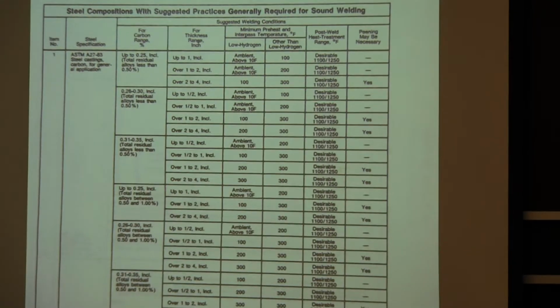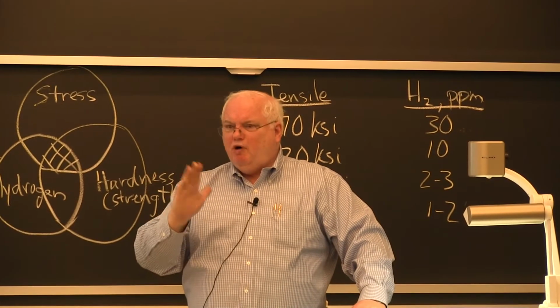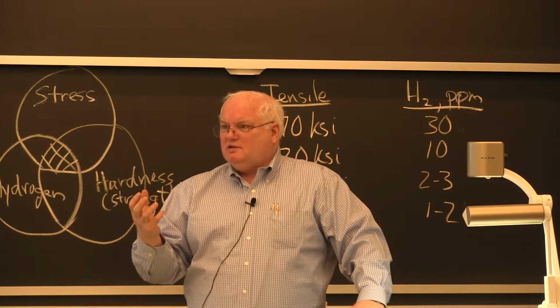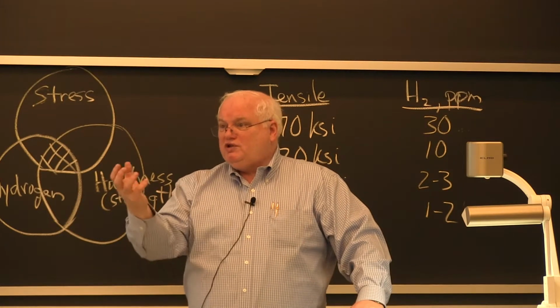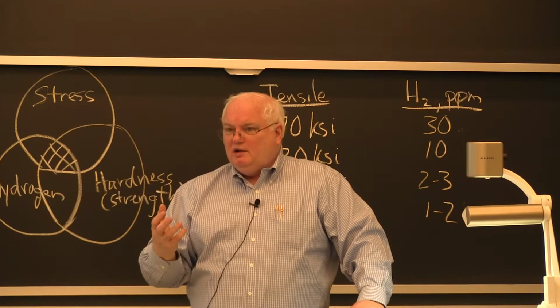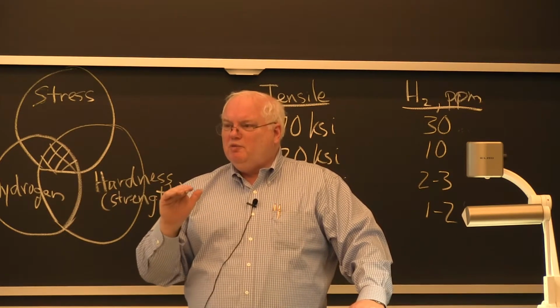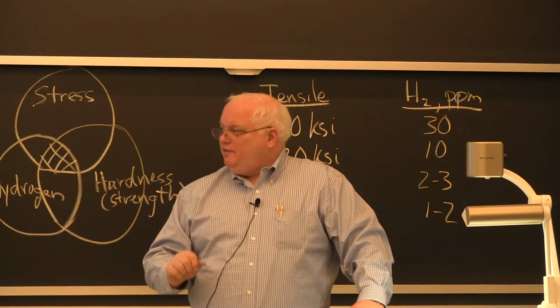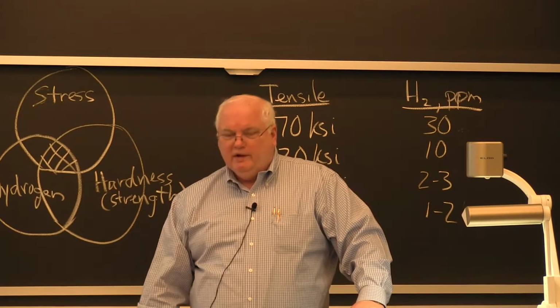I think it took them 3 days to weld that, okay? 24 hours a day, okay? To put in 400 passes, yeah. If you do too much, and that's the interesting thing about peening. A little bit of peening is good. It creates surface residual stresses, compressive stresses on the surface. If you over-peen, you're going to start getting like the peened head of a ball peen hammer that starts introducing cracks. And so over-peening can reduce fatigue strength. Under-peening will not, well, optimum peening will give you much better fatigue strength. Under-peening can give you low fatigue strength. Over-peening can give you low fatigue strength.